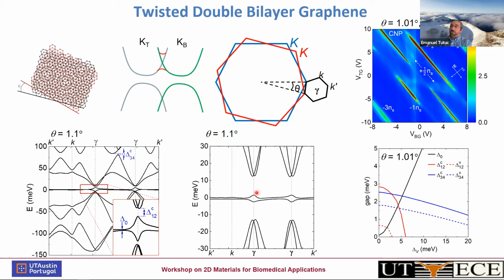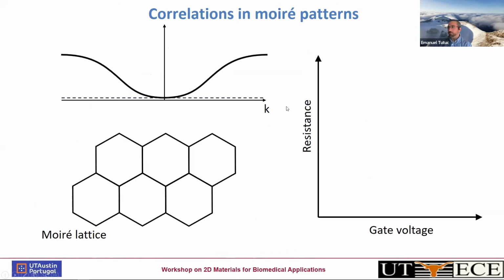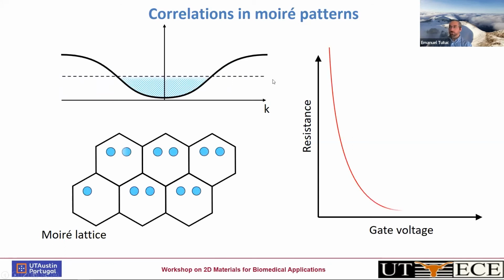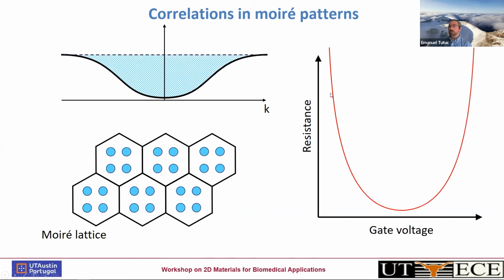These are calculations, so the bands can be very flat there. And the way to understand it is, let's say we take two parabolic bands. These would be the twist in momentum space, so this would be the two minima right here. And if they hybridize, this steepness right here disappears, and we end up with a relatively flat band. Let's see what happens when we try to populate flat bands with the gate. So this is an energy momentum dispersion. And then if we were to populate it with electrons, we put 4 electrons per unit cell, 2 per spin, 2 per valley.